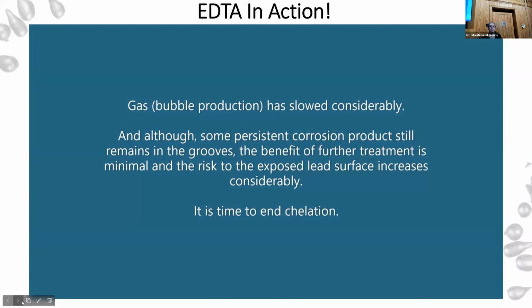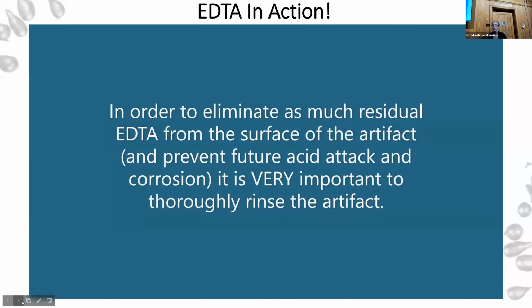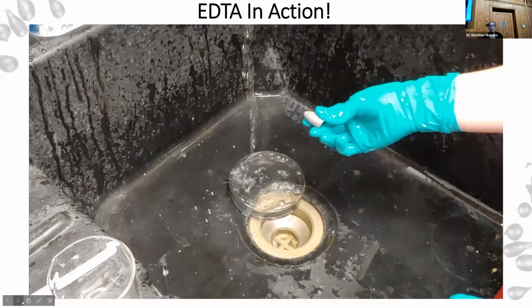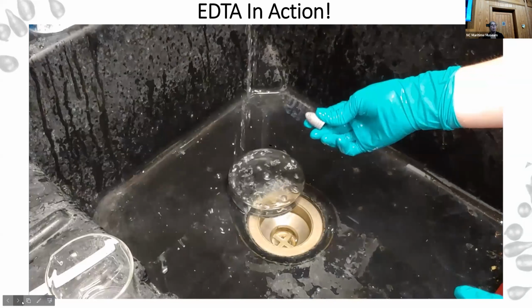With EDTA, sometimes we have problems with not rinsing thoroughly enough to remove all that residual acidic content, which can lead to further corrosion. So it's very, very important to rinse the artifact thoroughly. Usually you rinse it for about the same period of time that it was in treatment. So if it was in treatment for 2 hours, you need to rinse it for at least 2 hours, sometimes more. Sometimes you can leave them in for 24 hours just to make sure that you've really diluted down any acidic content that's still there and removed any of that chelator as well.